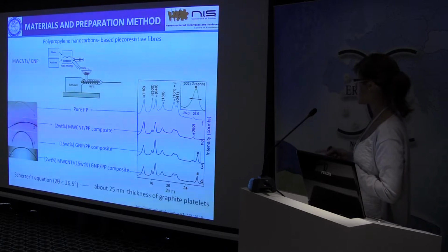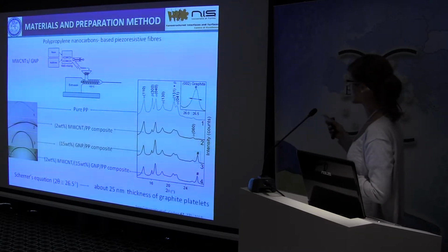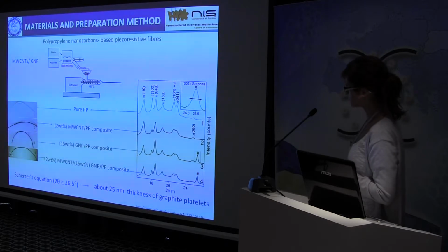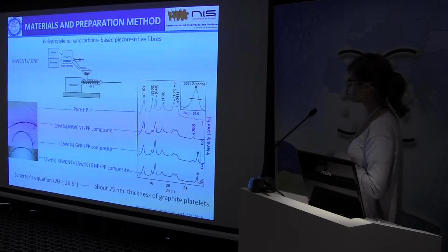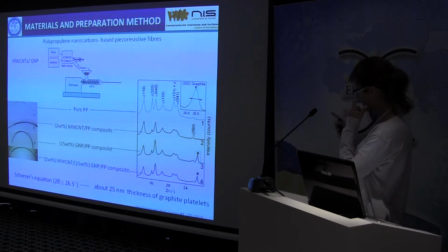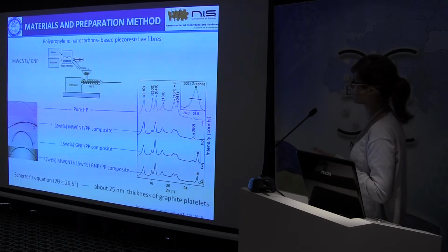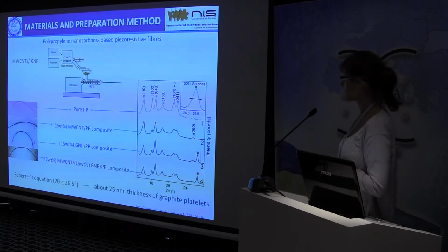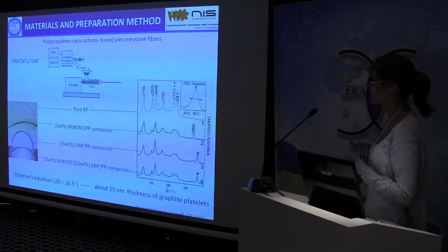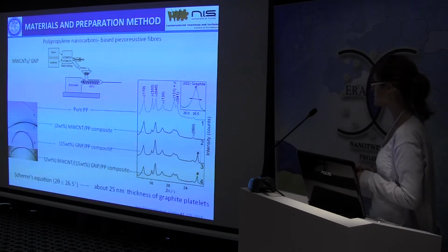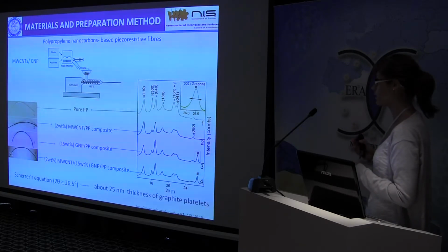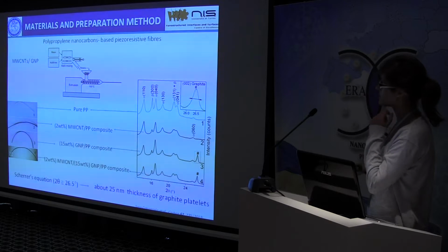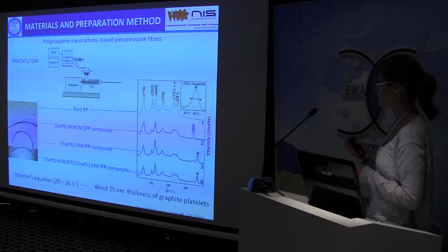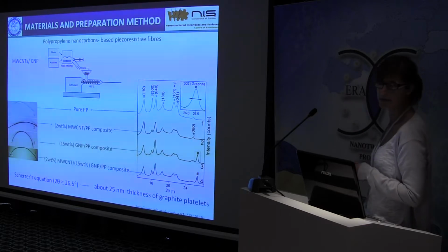Here you can see the peaks of polypropylene and another peak at 26.5 degrees, which you can see in the inset. This peak is due to the diffraction of the 002 plane of the graphite. Then finally the second pattern refers to the composite which contains only multi-wall carbon nanotubes, and here there is no peak at 26.5 degrees, probably because the quantity of multi-wall carbon nanotubes is very low, about 2% by weight, and because the crystallinity of this kind of multi-wall carbon nanotubes is very low compared to the crystallinity of the graphite nanoplatelets we used.